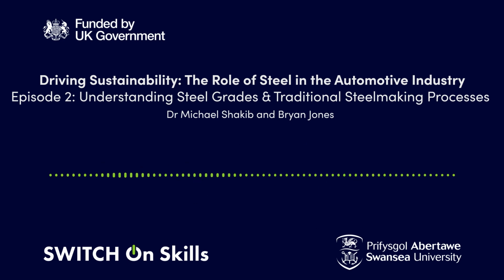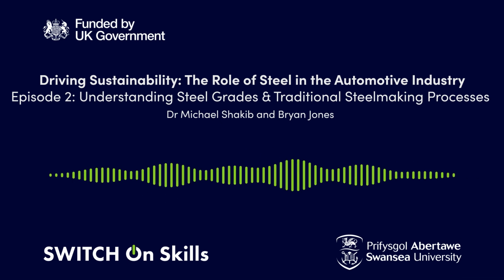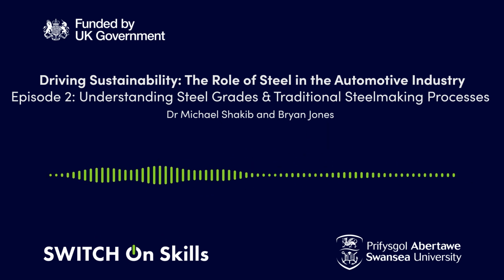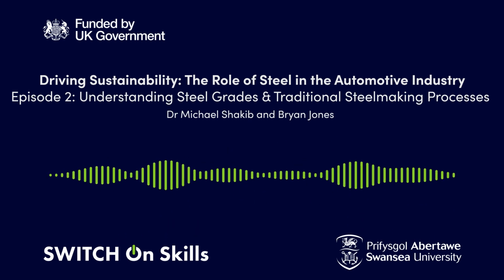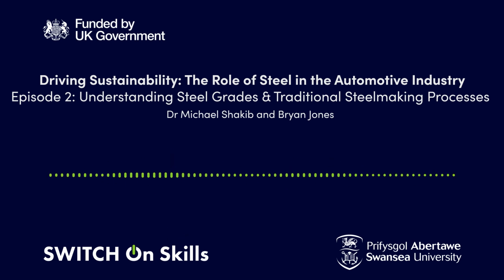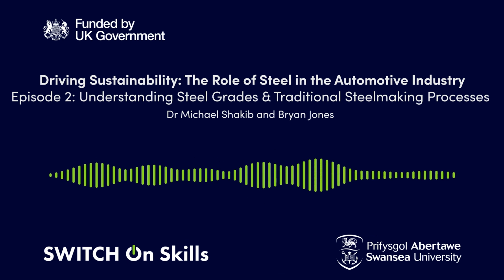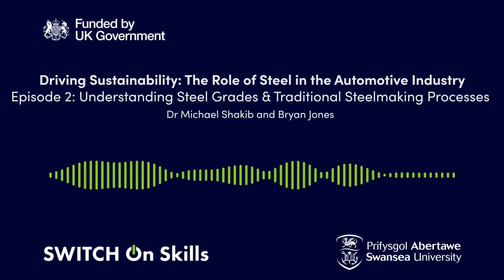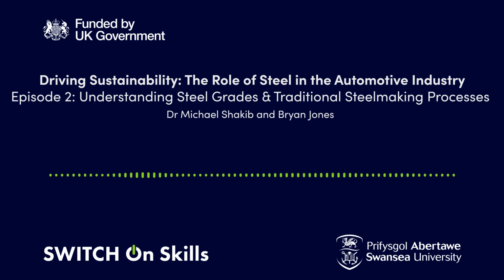Okay then, Bryan, so we've got these processes. We've got our blast furnace and basic oxygen processes, and now the electric arc furnace, along with the other two processes that you've just mentioned. Yes. So no matter what process you use, we're going to be producing carbon dioxide. So I mentioned earlier about the numbers. And we said, what was it, about 1.8 tonnes? It's 1.8 tonnes of carbon dioxide to 1 tonne of steel, predominantly as a consequence of blast furnace operations. So that's 90% of the carbon dioxide emissions from the blast furnace basic oxygen steelmaking route.